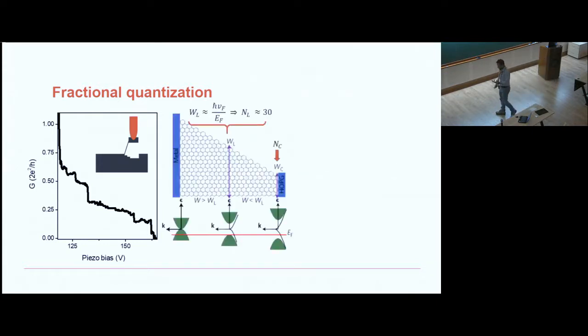So what Vijay and Adip said is that what could be the case here is that now the two edges are talking to each other, because the edge state, the state which is supposed to be a metallic state, is no longer, this is not a semi-infinite graphene, but this edge is starting to see the other edge. Okay? And this means that there is now a transmission, a reflection back, and hence the transmission coefficient is no longer 1 anymore.